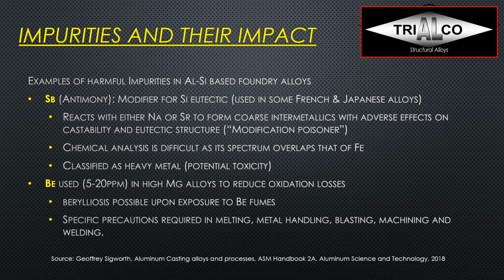And then we have beryllium, and I mean, we have been using beryllium without any problems for decades, but it is used normally just in high magnesium alloys, so it's not a commonly used element in many alloys, not in most of the 300 series alloys, but it's used to reduce oxidation losses. What was found then at one point in time is that you can develop berylliosis upon exposure to beryllium fumes or smoke and dust. You have to be careful, especially when you're melting, of course, the melt handling, and then blasting, machining, welding, or hand polishing the surface of castings that are containing beryllium.